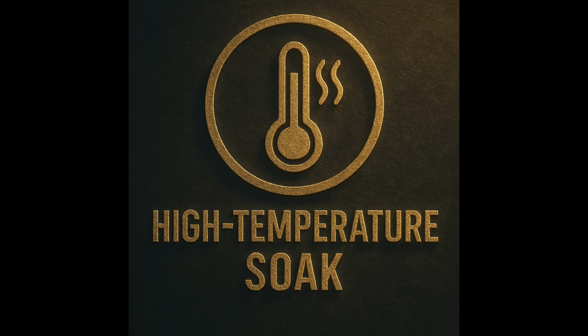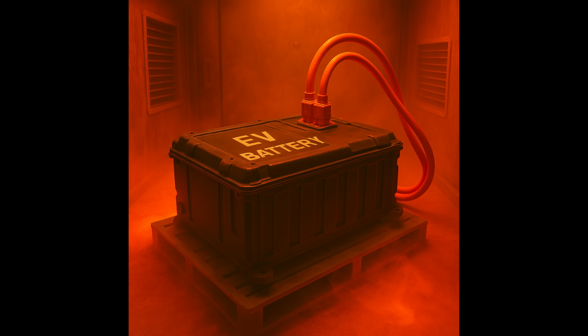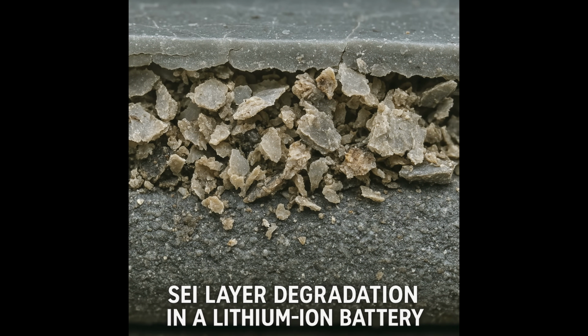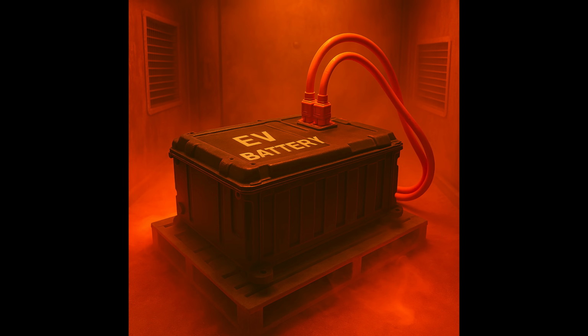Next up, let's look at high temperature soak conditions. As temperature increases, the electrolyte becomes less viscous, almost like water at extreme temperatures. This improves ion mobility, reducing internal resistance and enabling faster charging and discharging. However, this improvement comes with thermal trade-offs, including chemical stability risks. The same high temperatures can accelerate electrolyte decomposition, such as solvent breakdown and SEI, or solid electrolyte interface layer degradation. It also generates CO2 and CO and hydrofluoric gases.